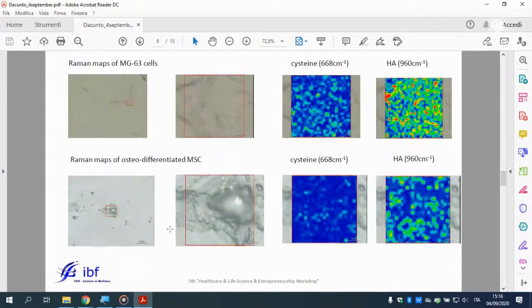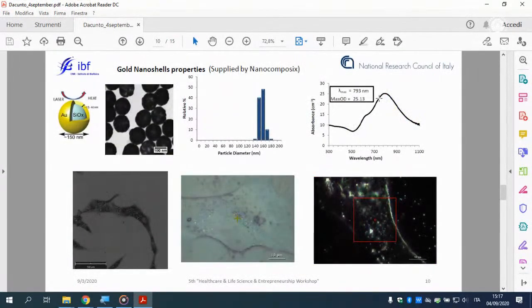And so performing Raman maps on the different cells, for example looking at cysteine and hydroxyapatite, we have a different distribution of such components in cancer cells with respect to osteodifferentiated mesenchymal cells. And generally, red means a very high intensity of such components.